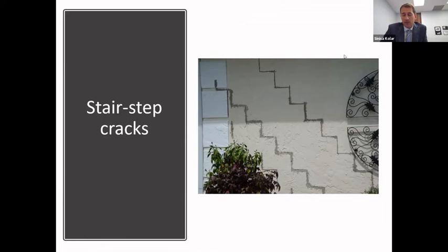I don't recommend this being done purely with a paint. This would first have to be routed and sealed in some manner using some sealant to create a proper substrate for your paint application. However, if the water has gone behind the stucco and started delaminating the stucco beyond what the crack shows, you would probably have to chip the stucco off the building, prep the surface properly, and then reapply stucco, potentially solve any issues with the substrate, put the stucco back, and then paint using appropriate paint.